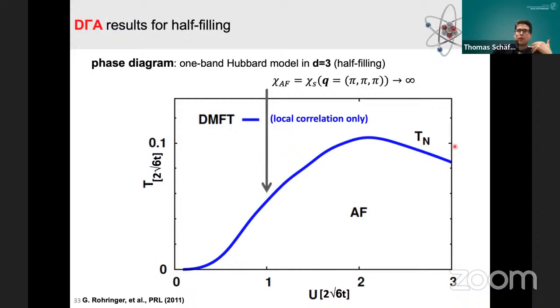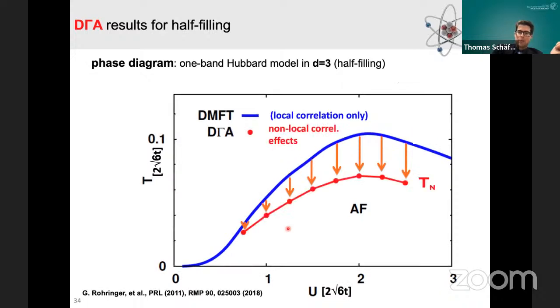How did we calculate this? Well, in DMFT, we also can calculate susceptibilities, not only spectral properties. In this case, the antiferromagnetic susceptibility, which I introduced before. And where this quantity diverges coming from above, there we have the phase transition. If we now include non-local correlations again, by means of the dynamical vertex approximation, DΓA, we see that this Néel temperature drops a bit. And this is due to the fact that these non-local correlations destroy the order in this intermediate regime.